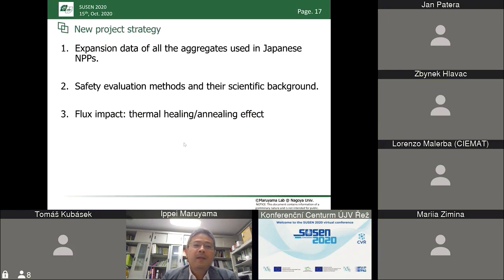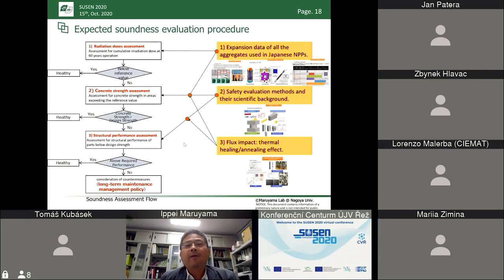When we think about the expected soundness evaluation procedure, first, we can use the neutron fluence. If we set a certain reference value, and the fluence is less than that, we can say that this is safe. And once this is violated, we can evaluate the soundness of concrete by using the concrete strength of the biological shielding wall or RPV pedestal structure. And even if the concrete strength in some part of the concrete member doesn't satisfy the required design strength, in this case, we can evaluate the structural performance. But for all of these three, we don't have enough data.